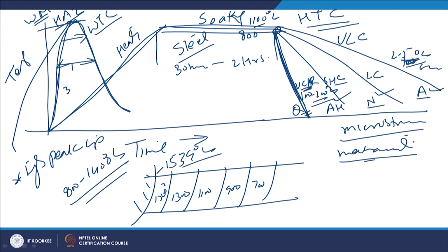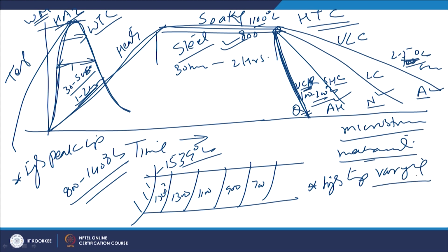This may be like 30 to 50 seconds, or as per the welding process it may be longer, like 1 to 2 minutes, but this time is not as high as which is observed in case of the typical heat treatment cycles. So, there are two aspects. One is the high temperature which is varying from the base metal to the fusion boundary, and the high temperature retention period. This is very short as compared to that of the typical heat treatment cycle, and therefore, this has a huge implication as far as the phase transformation is concerned.